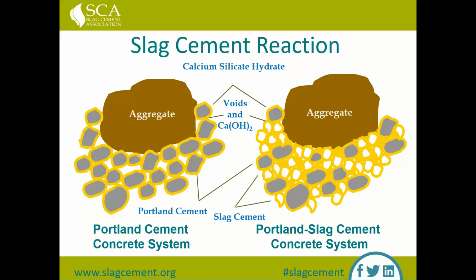From a physical standpoint, you've got your particle size distribution, the shape of the particles, that sort of thing, and so you are getting some particle packing, which helps densify the product. Second, you're getting some benefit from reaction of the slag with the calcium hydroxide to produce more CSH - more of the calcium silicate hydrate.